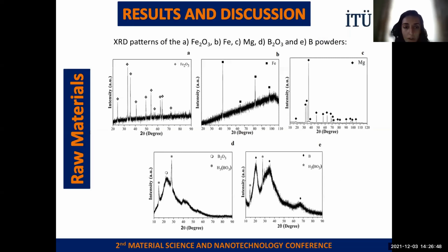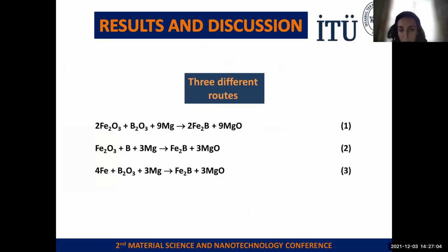And these are the XRD patterns of our raw materials: iron oxide, magnesium, boron oxide, and boron nanoparticles. Boron oxide and boron include an additional phase because of the humidity. And also, 3 different routes and 3 different powder batches were prepared, and then filled into the milling vials, as we mentioned before, these 3 different powder mixtures.